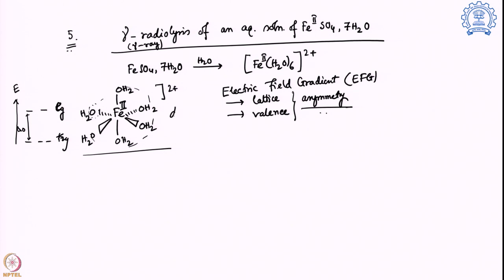Now, iron 2 is a d6 system. So this will go 1, 2, 3, the 4th electron will go over here, the 5th electron here, the 6th electron comes over here. So now you can see Eg is symmetric, T2g is asymmetric because of one extra electron on the lower spin. So that is why the valence contribution exists, and the lattice one does not, in the beginning. So what do we expect? That there will be a quadrupolar splitting because of the presence of the valence interaction.